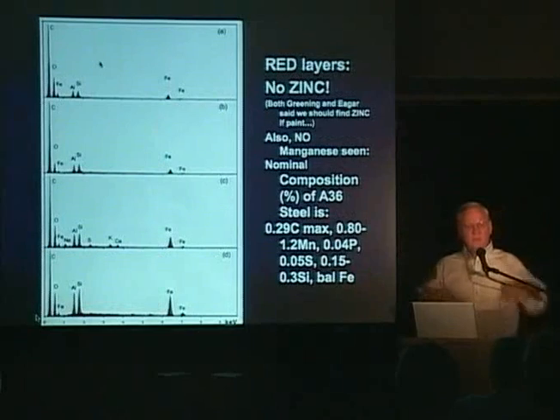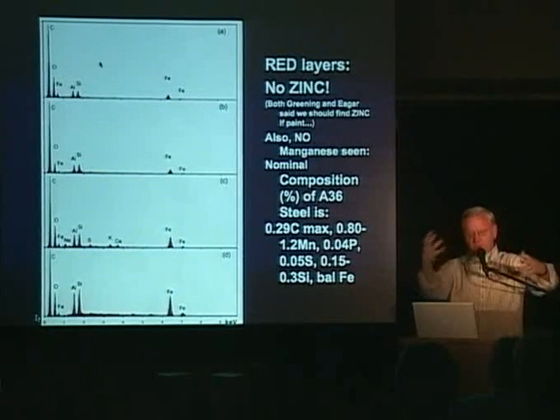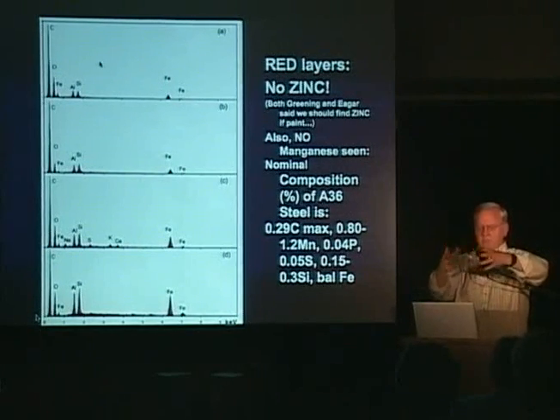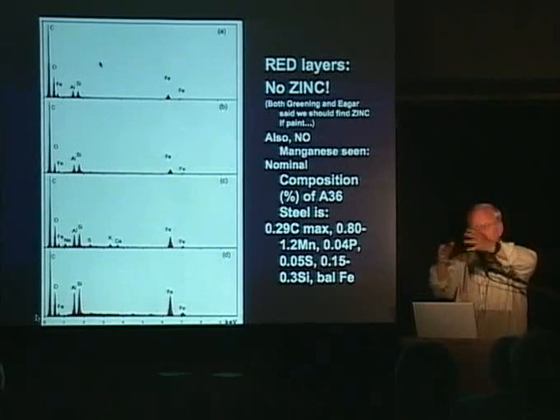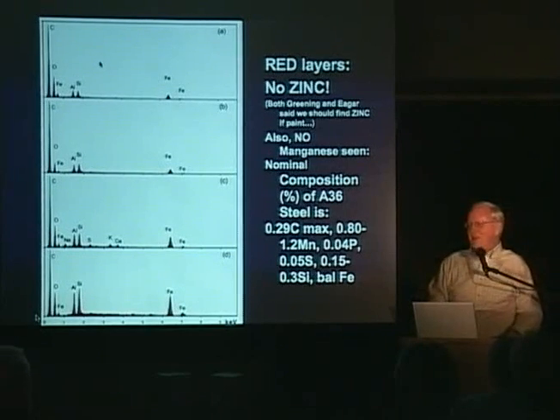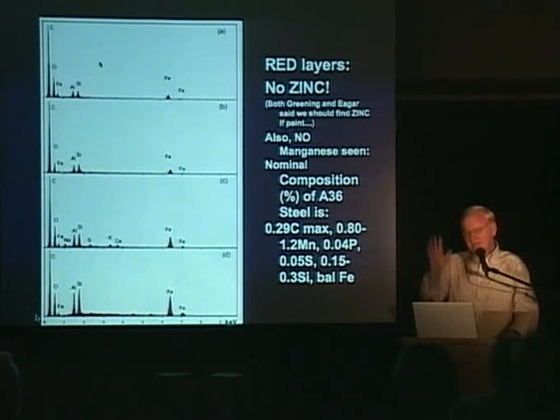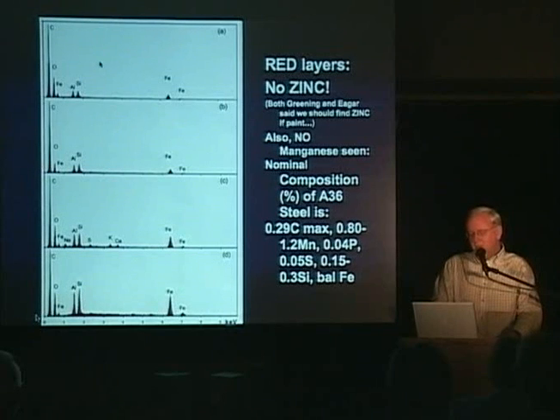And others have said, well, maybe as the buildings fall, you just get a mix of aluminum and zinc. It mixes up, and you get this wonderful red stuff. Sorry, where's the manganese, first of all? And where's the other junk that we find in the dust, which is zinc and chromium and calcium and so on in abundance? But those are not seen in abundance. There's a little apparent contamination in 3, but the characteristic signature does not show any zinc or manganese.